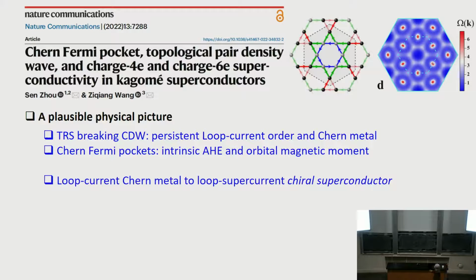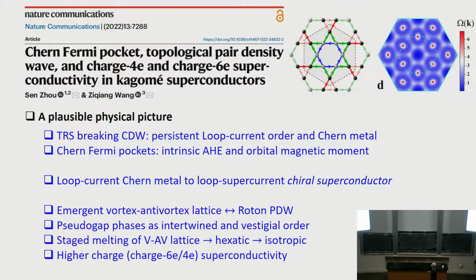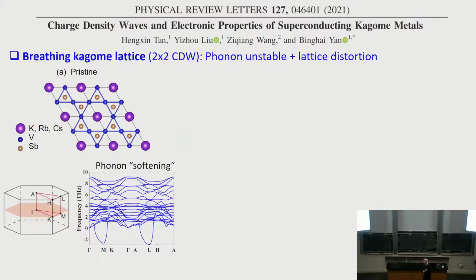Then I'll talk about what's going to happen to these loop currents once you go to the superconducting state. These loop currents have to turn into loop supercurrents in the superconducting state. And the supercurrents must go around vortices or antivortices. So this will be a state of spontaneously nucleated vortex-antivortex lattice. And once you have a lattice, it carries a momentum, and that's what the Roton PDW, pair density wave, is all about. And there is a pseudogap phase coming out of vestigial order when you try to melt such a superconducting state. And I'll hopefully have time to talk about higher charge superconductivity that emerges from this picture.